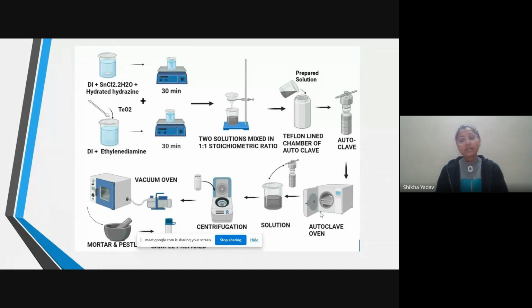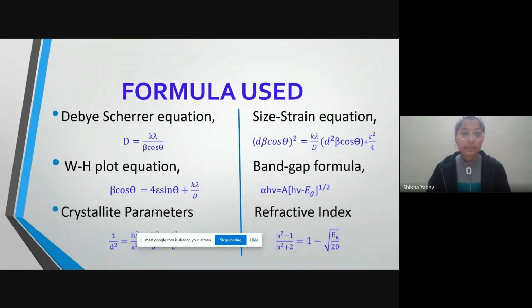After that, it was taken out and kept for cooling for 24 hours. The solution was then taken for centrifugation using DI water and ethanol. Finally, we moved our sample to the vacuum oven at 100 degrees Celsius to dry it. After that, the sample was ground in a mortar and pestle, and then we got the prepared sample. So this was the methodology that I followed in my research to prepare the tin telluride. These are some of the formulas that have been used in my research paper. Three formulas, the Debye-Scherrer equation, the size-strain equation, and the WH plot, have been used to find the crystallite size and strain.